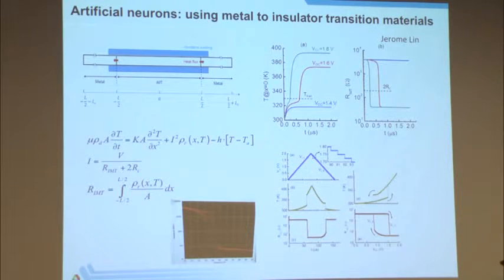A second example, and this is work that Jerome Lin, who is another postdoctoral associate colleague of mine here, is focusing on. This is now trying to make an artificial neuron, but using a metal to insulator material. If you take something like vanadium oxide, many of you are familiar with it, it has a thermal metal to insulator transition: if the temperature exceeds 70 degrees C or something like that, its resistance drops. If you grow good vanadium oxide, its resistance can drop by about 5 orders of magnitude. So the question is, can you use that as an integrate and fire neuron?